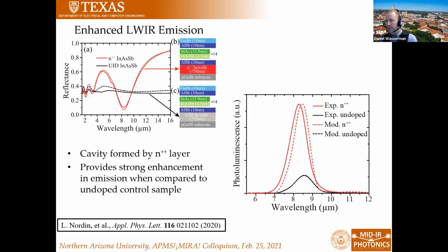So the short answer is, we of course are limited by the real world, namely losses. And as much as I would love to be someone who doesn't have to worry about losses, it turns out that they're rather significant in any plasmonic material. Now we have a purely single crystalline, epitaxially grown plasmonic material, so I feel pretty confident that as things go, we have a good quality plasmonic material. That doesn't mean that there are no losses.